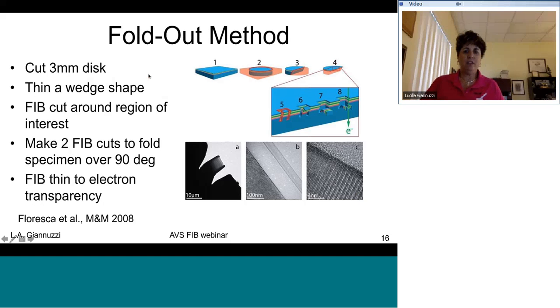Fold-out method, another way to make samples without FIB lift out. So the sample was thinned, cut into a 3mm disc, thinned some more and angled, and then the FIB was used to mill out this little wedge-shaped sample.